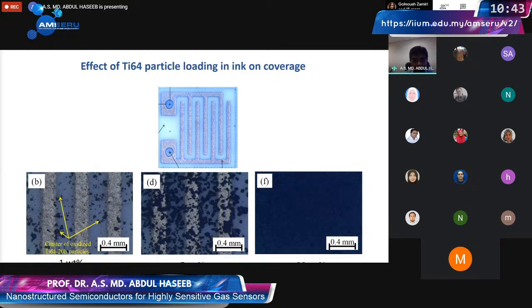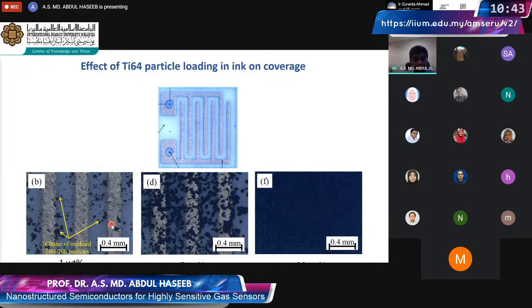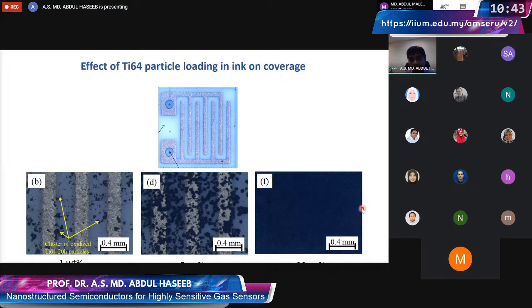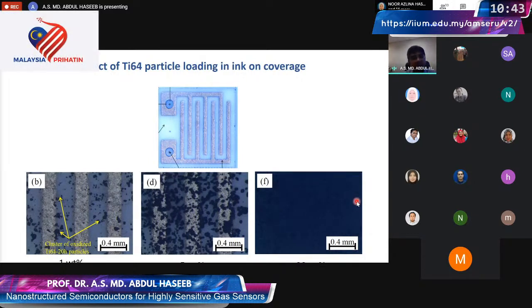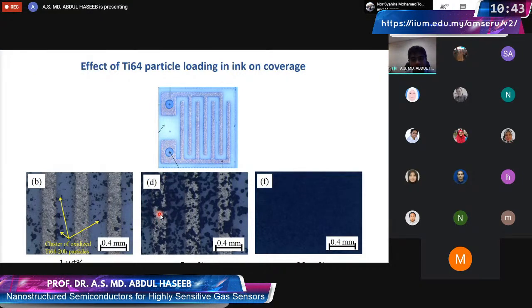And we need to carry out some optimization, because we varied the amount of solid nanostructures in the ink, and we varied it from 1 to about 20%. And what we see is that when the loading of the particle in the ink is very small, then the particles do not bridge the gap. So we have high resistance and they cannot work as the sensors. On the other hand, if we have a large amount of particle loading, then we create a very thick layer. And this is also not good for sensing, because they actually short the whole thing and we don't get the change in resistance as a function of gas. So we have, again, one condition where we optimize them and they just touch each other. And in doing so, they do not short the whole system.